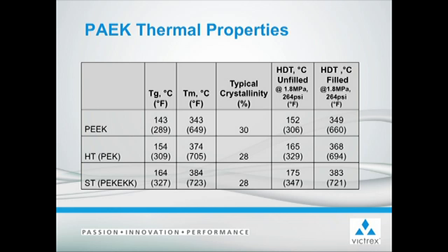And this table is just a recap of the thermal properties of each of the different grades, including glass transition, melt temperature, HDT, filled and unfilled for each of the different base resins. It also shows that each of these have a similar level of crystallinity, and beyond what's on the table, mechanical properties, for example, tensile strength and modulus, are all very similar, as well as the chemical resistance of each of these grades is also very similar.